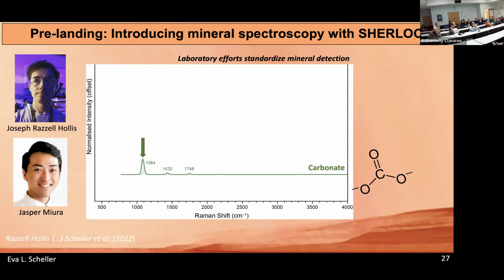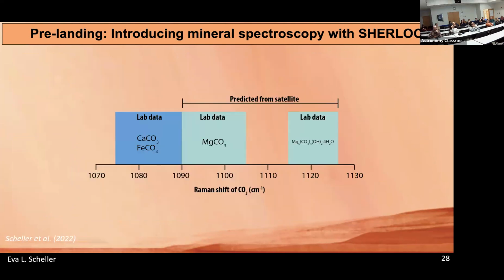So here you can see, we're tracking again this Raman shift property that I talked about, and just intensity on the y-axis. And for the carbonate mineral here, we're tracking this main primary mode that you can observe a nice Raman peak there. All right, another thing that you can do with Raman shift properties is that depending on which cation species, so remember I talked about cations combining with carbonate anions, depending on which cation species you have, they're going to shift the Raman shift vibrational mode up or down.